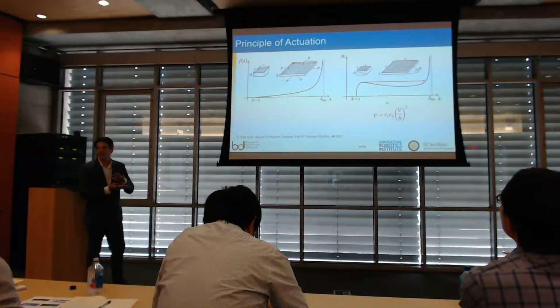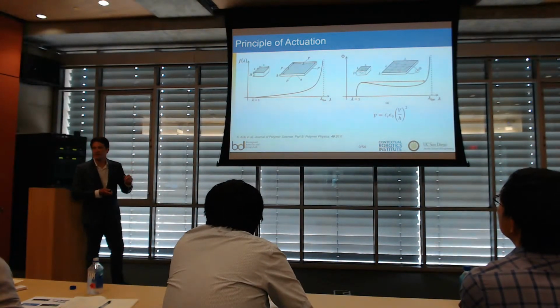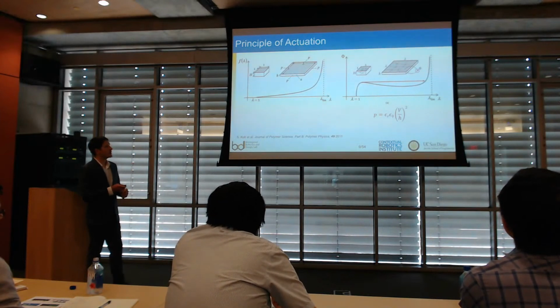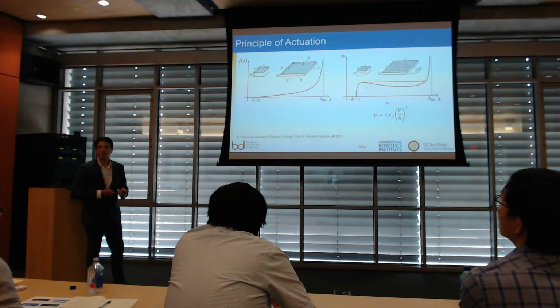And so if you make the material too thin, it might break down before you can actually get to that snap point. And so for the longest time, researchers were limited by this case here, to where they could get to, say, 30% strain before it would break down. But then what researchers found is that if you stretch the material ahead of time, you can actually change when the material will break down. You can get improved performance by it.